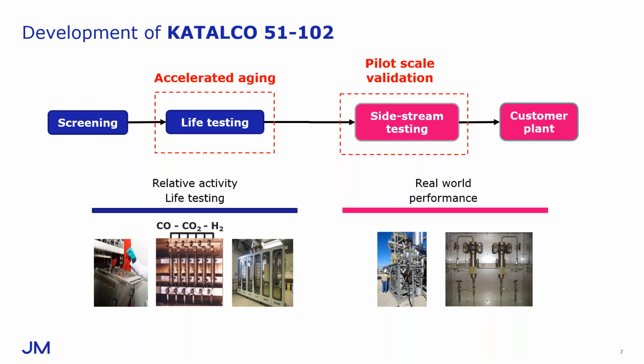So to get over this problem, we had to design and build an accelerated aging microreactor system, and also develop aging protocols that would allow us to condense the equivalent of many months or even years of deactivation under plant conditions into just a few weeks of rig time. And once we had this system in place, this allowed us to evaluate the aged activity of different formulations in a very short period of time. And also by operating under a range of conditions, we were also able to use this system to generate data to help us to optimize our deactivation models.